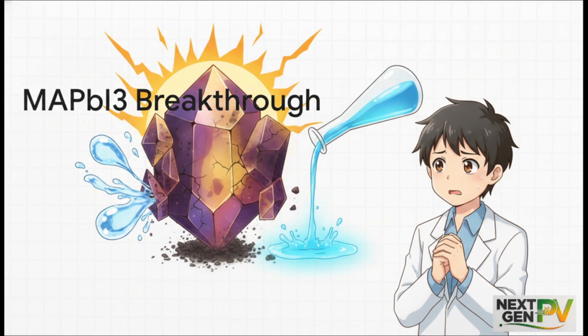That was MAPbI₃, or methylammonium lead iodide. It showed us we could literally print highly efficient solar cells from cheap liquid solutions instead of using expensive high-vacuum chambers. Total paradigm shift, right? But it had glaring flaws. It degraded rapidly around moisture, its organic parts would essentially cook out under extreme heat, and of course, it contained